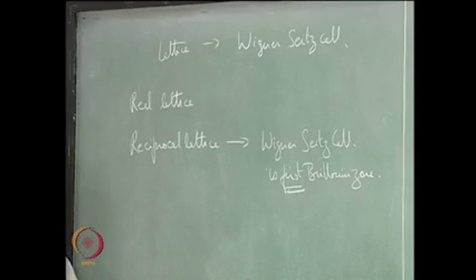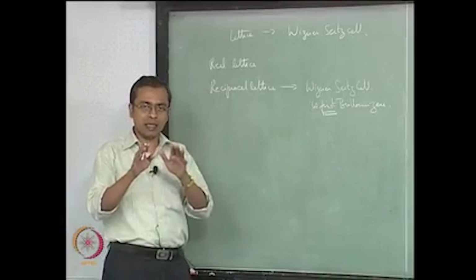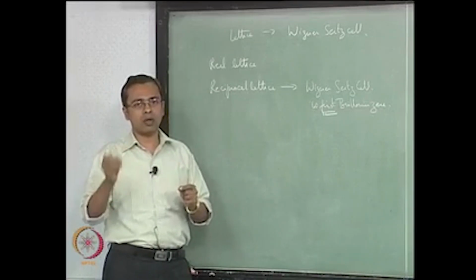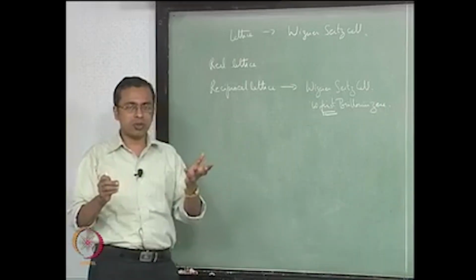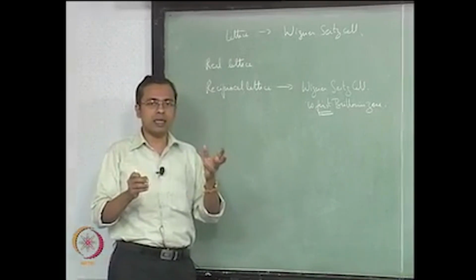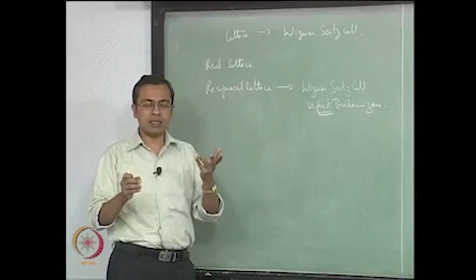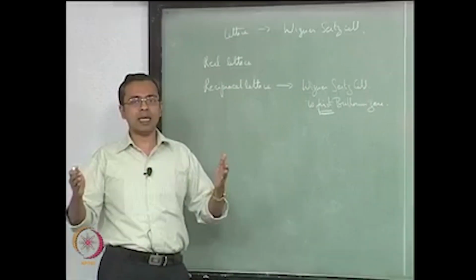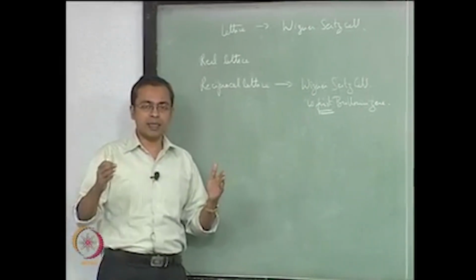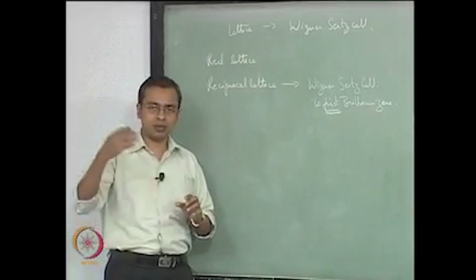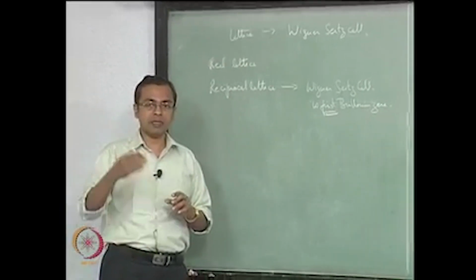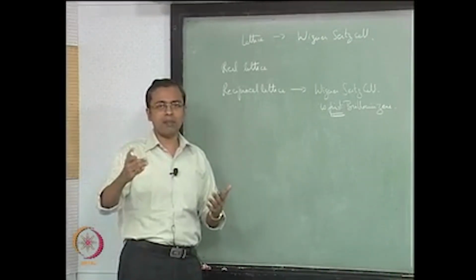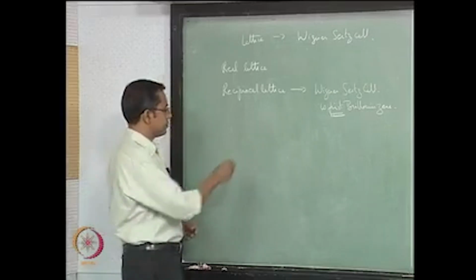Instead of talking of lines we have planes, and all those planes intersect along lines, and so the shapes that we identify start beginning to look complicated. Okay. So I have been able to show you the first Brillouin zone rather clearly. If you look at the second and third Brillouin zones in 3D, it looks rather complicated, but the process is exactly the same. You simply keep identifying planes that bisect the reciprocal lattice vectors to further and further neighbors, and then you keep identifying the structures where you cross only one Bragg plane and no further Bragg planes.